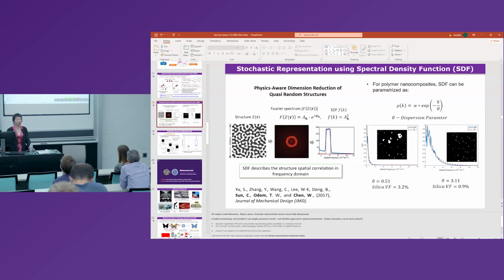There are actually, in the literature, the gamma curve and the Gaussian model that will be sufficient to describe many different kinds of material systems. But they have to be something like this. It's particle based, but it could be free form. It doesn't have to have this round shape. But this method is not going to work for, say, this morning I talked to one of the colleagues here about ceramics and defects, those that don't have periodicity. It becomes very difficult. So here we assume there's a periodicity, that from one region to another region, this pattern repeats. Yeah, that's what I was trying to say.